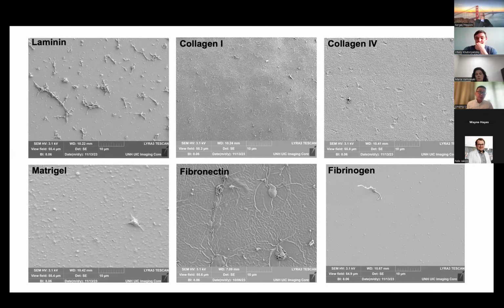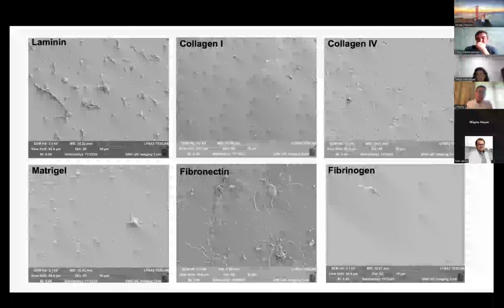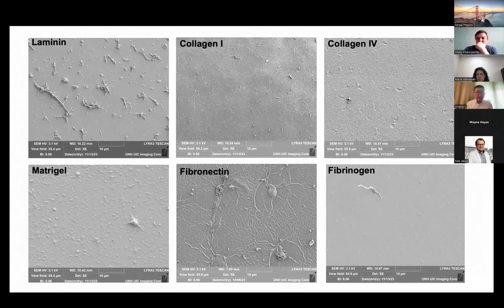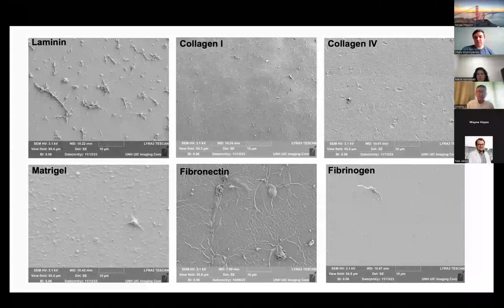So we're now using 6 commonly applied types of ECM proteins: laminin, collagen 1, collagen 4, matrigel, fibronectin, and fibrinogen. You can see, and these are SEM images, that we have different morphologies and actually capture some of the native ECM morphology that has been adsorbed onto the surfaces. So this is really interesting to us, that we can generate more generalized substrates that allow adsorption of a variety of different ECM proteins.